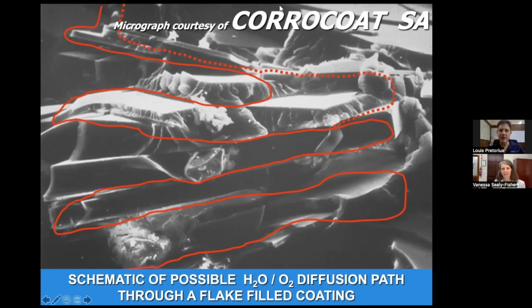Absolutely, Vanessa. So we've glued in 100 layers of flake or more, and that's given us the diffusion time, and that path length ultimately gives us life expectancy. Because if it takes a longer time period for a water molecule, something innocuous, to diffuse through the coating, it just means that the coating is going to last so much longer. And that's why the glass flake coatings under very arduous lab test conditions tend to outperform the same resin system that is unreinforced. Yes, I think that was really helpful. And for someone like myself who doesn't have much experience in reading micrographs, it's really helpful to have the red lines there to show me where I'm looking.